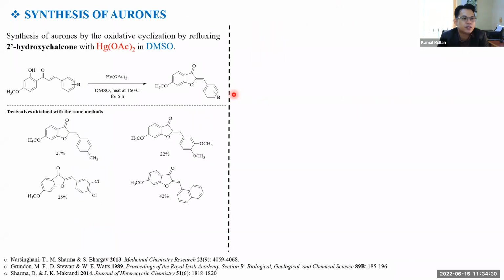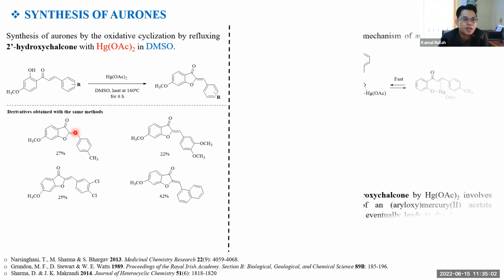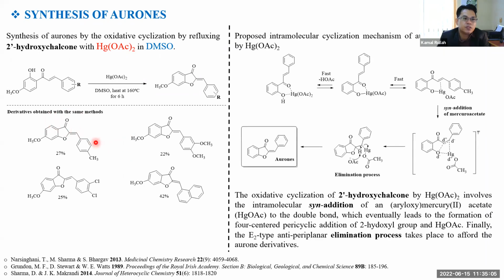Now we talk about how to synthesize aurones via chalcone. We successfully synthesized aurone by oxidative cyclization by refluxing 2-hydroxychalcone with mercury acetate in DMSO. We have some of the derivatives, with a bit low yield, depending on the raw material and moiety. This is a sample, and this is the proposed intramolecular cyclization mechanism of the aurone ring formation by mercury acetate.